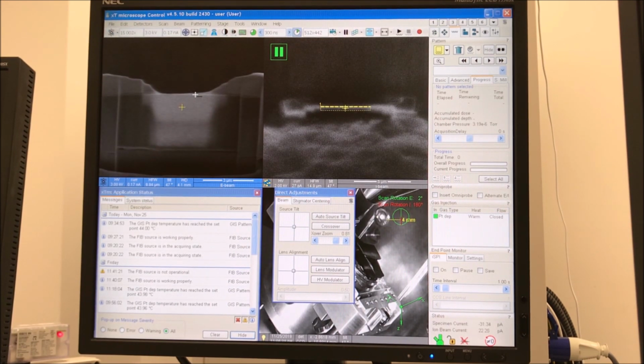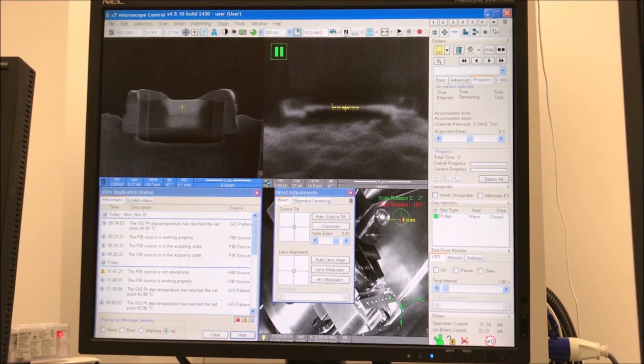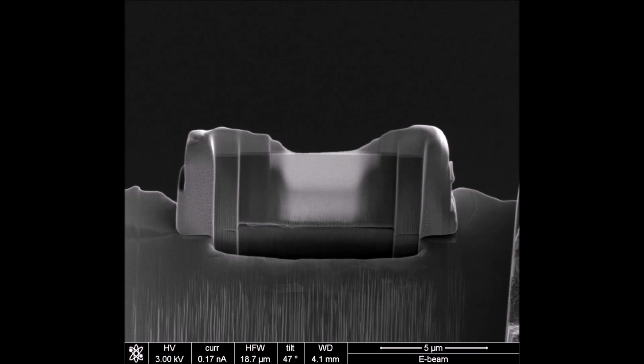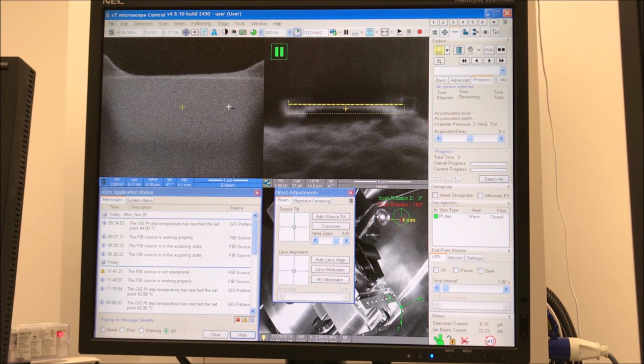So the lamella is now done. You definitely do not want to do any more ion beam imaging at this point because you're going to end up damaging your sample. And you don't want to do really any more e-beam imaging either, although I'm going to go ahead and take a photo here so you can see again the final result, which I showed you already previously. And I'm going to go ahead and mag in here and take another photo so you can more clearly see that near surface region and that film that we're interested in imaging.